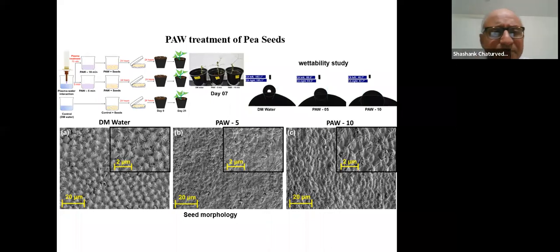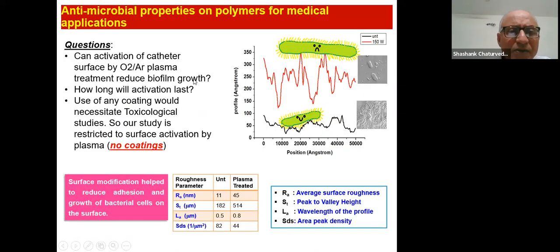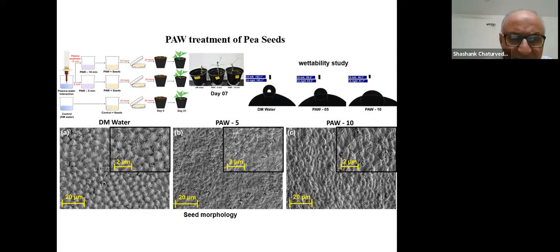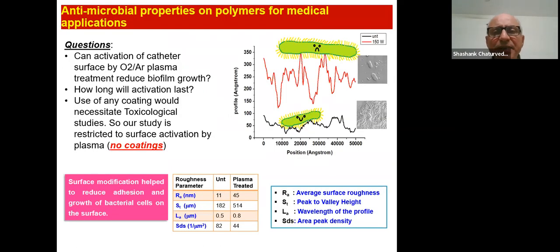The same plasma activated water has been studied by some of our agriculture collaborators. We are working with some agriculture universities, Solan, Anand, and so on. They found that if you have seeds and you put them in plasma activated water for a certain amount of time, it tends to enhance the rate of germination of the seeds. Number one, basically what it does, it modifies the surface properties of the seeds. So the seeds start taking up water faster. Because of that, the seeds germinate faster. The amount of chlorophyll you get, the total growth of the shoot and so on, all that becomes faster. Now, finally, of course, somebody has to study whether there are any harmful effects being produced by this. That is currently being examined. And many of these things are being done through BRNS projects. We have collaborators in different sectors.